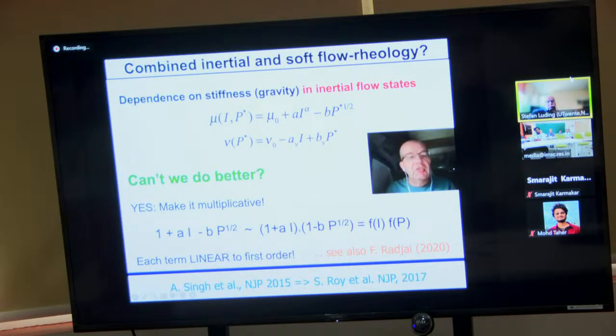So in my definition, we take the additive thing, but we replace it by a multiplicative thing, because that's much more handy. The additive terms come out from the multiplication, but there's also a nonlinear term popping up, which is hard to quantitatively deduce from particle simulations, but might be there. And the multiplicative rheology has the advantage that it's directly involved. Each of these first order terms here is linear, actually linear in time scales, not in pressure. The nonlinear term definitely is not linear, but we have a first order linear model this way. We did this in 2015 and later in 2017.